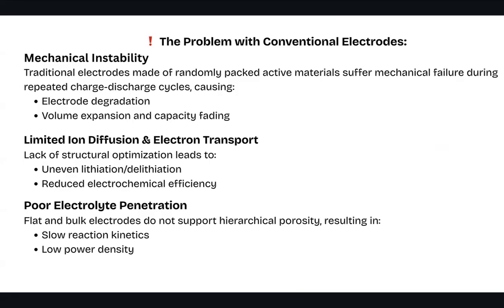The second problem is limited ion diffusion and electron transport. The lack of structural optimization leads to uneven lithiation and delithiation, and hence reduced electrochemical efficiency. The third problem with the conventional electrode is poor electrolyte penetration. The flat and bulk electrodes do not support hierarchical porosity, hence slow reaction kinetics happens, hence low power density takes place.